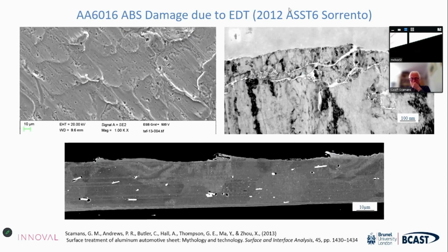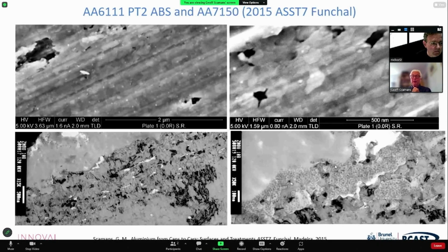This is another one of my bugbears, which is electro-discharge treatment of rolls before the final pass of aluminium automotive sheet. It's done for steel. It absolutely doesn't have to be done for aluminium, but again, the German OEMs like it, so it's still put on. But the work at Manchester was able to show that this is such a detrimental technique for the aluminium surface. You can see the shingle it produces on the surface, which is meant to be a good thing. But you can see the severe damage it does within the deformed surface layer, and actually makes a lot of pre-cracks, which is not a good idea if you want this surface to have good corrosion resistance. I still haven't managed to persuade people that this should not happen.